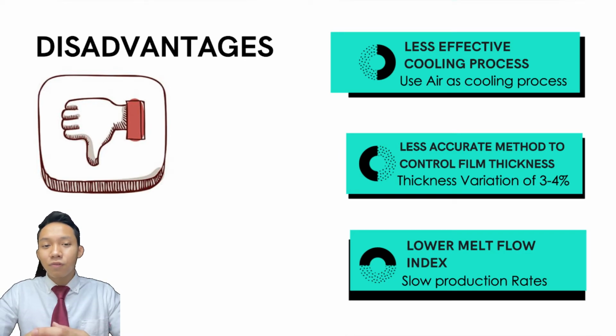The resins used for casting typically have a higher melt flow index, which is the amount of polymer that can be forced through a standard die in 10 minutes according to a standard procedure. The melt flow index for the cast film is about 5 grams per 10 minutes, whereas for blown film, it is about 1 gram per 10 minutes. Consequently, the production rates for the cast film are higher. Cast film lines can reach production rates up to 300 meters per minute, whereas blown film lines are usually less than half this value.